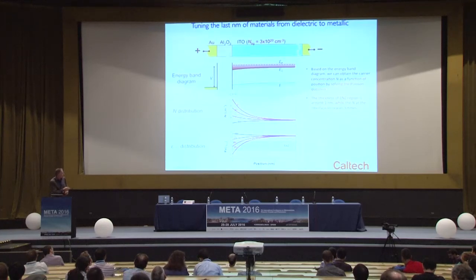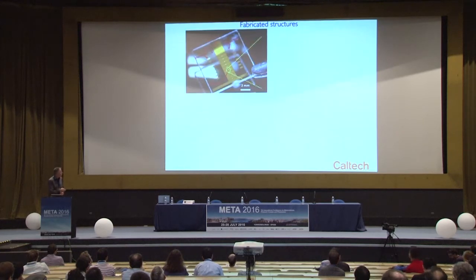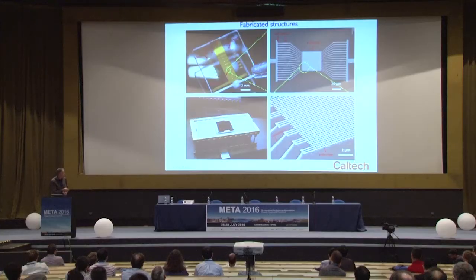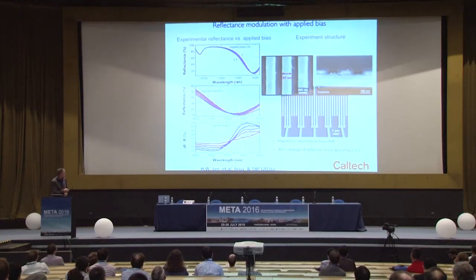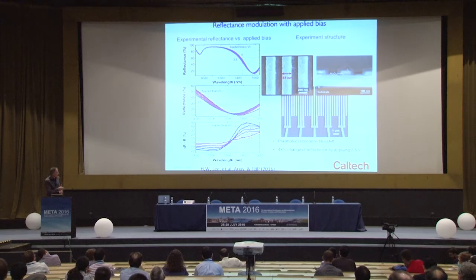By choosing the background permittivity and the voltage, we can now tune the permittivity from positive to negative with small applied voltages across the gate in the near infrared. This just shows an example of the structures that have been made, so we can actually see that this is a fairly integrated device structure. This forms a 1D array of subwavelength antennas. These antennas have resonant magnetic dipole resonances near the 1.5 micron regime in the telecommunications band, and this allows for a modulation of the reflectance of about 30% with a few volts applied bias.